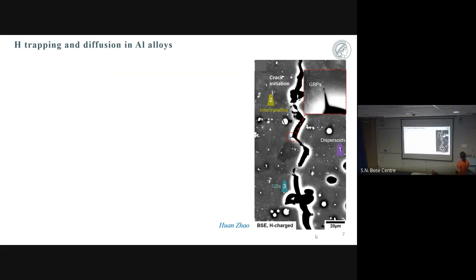I will start the discussion with this beautiful image created by my colleague Huan Zhao. This image is an electron backscattering image, where you see the 7XXX aluminium alloy, which I have just introduced, being electrochemically charged for long enough so that an intergranular crack is formed. Also, a uniaxial strain is being applied along it so that an intergranular crack is formed at the surface. Now we focus on the intergranular crack. This crack is important because the microstructural evolution around this crack surface is what we are mostly interested in.